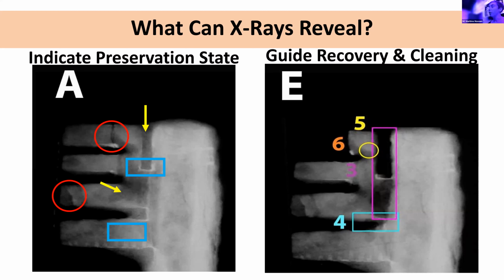And then we have areas where it's very, very exposed. You can essentially just see the entire black background straight through it. It's pretty much transparent. And these indicate portions where there may not be material anymore. It's either very, very delicate, not very compact corrosion product, or else we might have voids. So we might have missing material, or we might have damage. As you can see here, there's basically a big crack that's running underneath the corrosion.